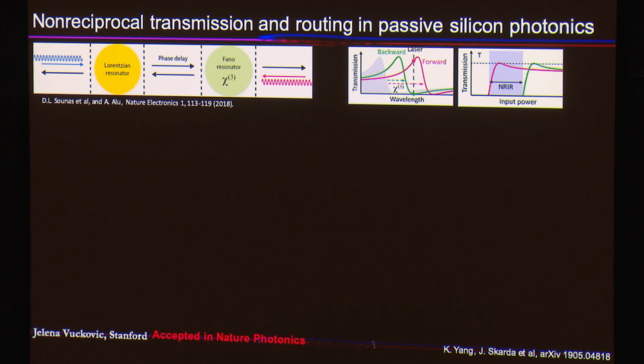So the idea is pretty simple. You have a cascade of 2 resonators, a Lorentzian resonator and a Fano resonator. You control phase delay between them, and you can design the system in such a way that coupling to the Fano resonator, and this is a Fano transmission, is different in the forward and backward direction. And if the system has nonlinearity, coupling of different power in forward and backward direction would shift the resonance by different amount. And as a result of that, at a laser frequency, which is constant, you will have different transmission forward or backward.